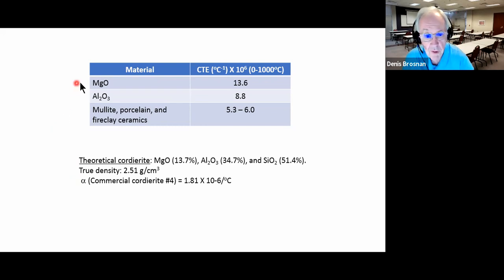Other ceramics like MgO are pretty high in thermal expansion, about 13.6 times 10 to the minus 6. I know it says times 10 to the plus 6 up here. That's what we multiplied this by to make a whole number. Alumina is around 8 to 9. Mullite, porcelain products, and fire clay ceramics are in the area of 5 to 6. Cordierite has a very low thermal expansion coefficient.